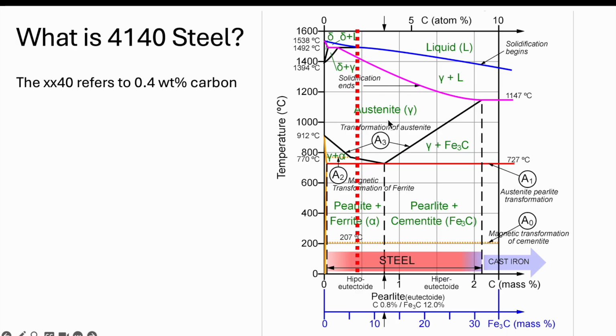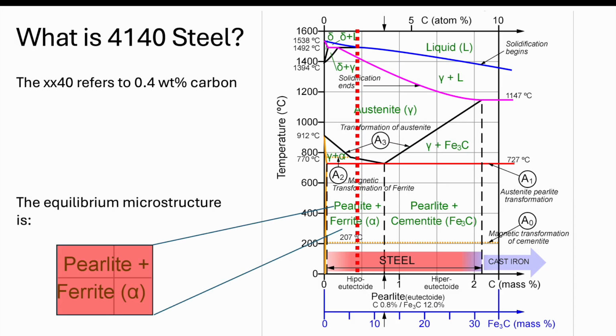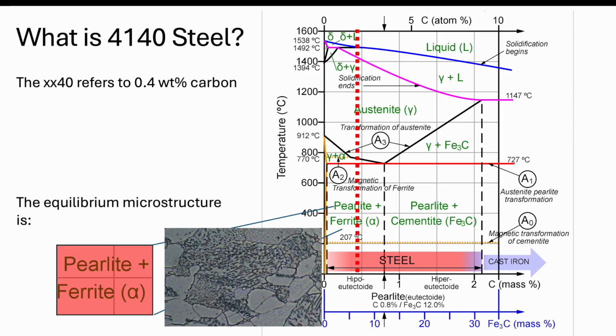At the higher temperatures, we have a phase called austenite. That is an FCC, or face centered cubic, structure. Upon cooling, we start to form ferrite. Then below 727 Celsius, we have a mixture of pearlite and ferrite. So our equilibrium phases are ferrite and cementite. We'll talk a little bit more about those in a second. And our microstructure is pearlite and ferrite, pearlite being a mixture.